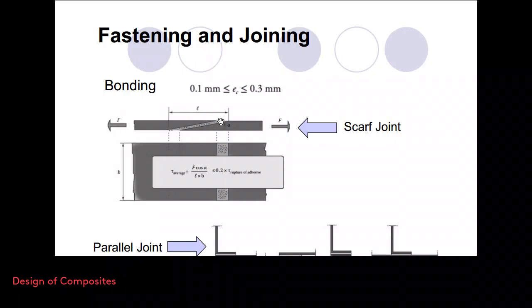As a result of this increased length, you have a higher area for the adhesion. In fact, you can predict the average stress in this case. If you apply a normal force, you apply force divided by cos alpha divided by length multiplied by the B. Sorry, B is the thickness of the laminate. I apologize. And then it has to be smaller than the rupture stress of the adhesive. Certainly you use a safety factor here as 5.